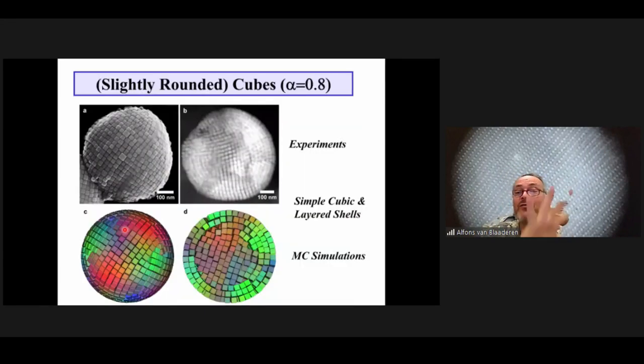To make a very long story short, we defined a shape parameter. 1 is pure sharp cube, 0.8 is therefore almost cube-like, and then we found simple cubic structures crystallize inside the superparticles. These are interesting, but for applications not that interesting, because if you burn away the ligands and the particles become one supercrystal, so when you do directed attachment, as it's known in the field, then you get just one clump of a single cube-like crystal.